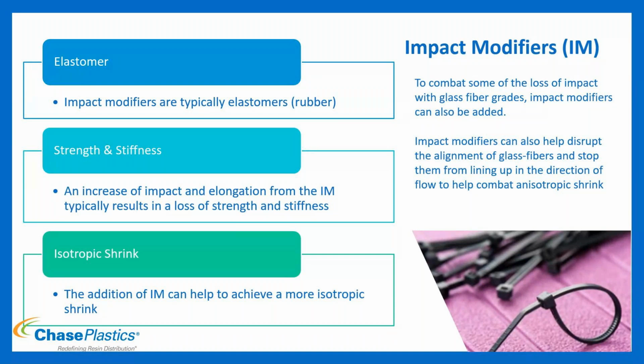The nice thing about your impact modifiers is they are also more spherical in shape, so they help with your anisotropic shrink. They do not line up in the flow direction like glass, and that helps you achieve more uniform shrink.